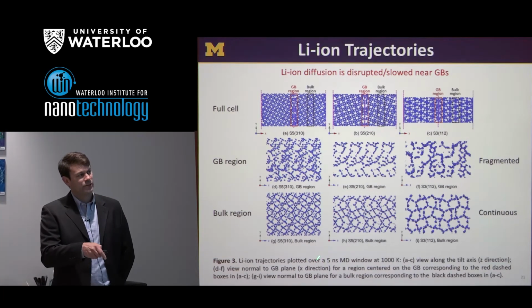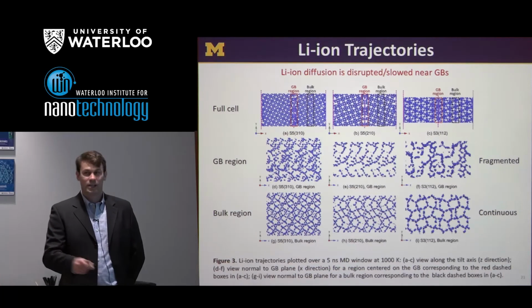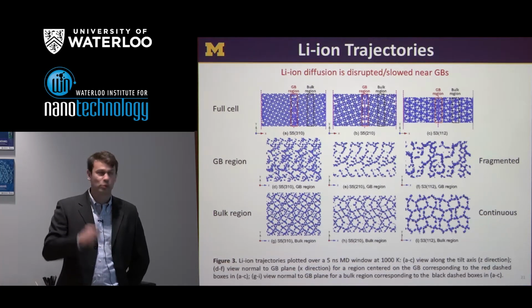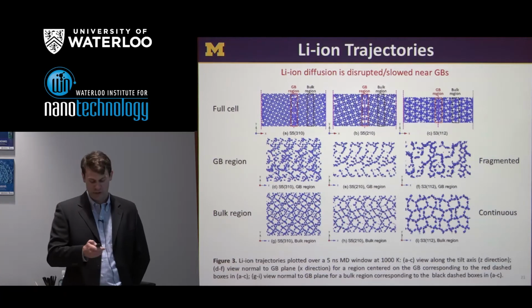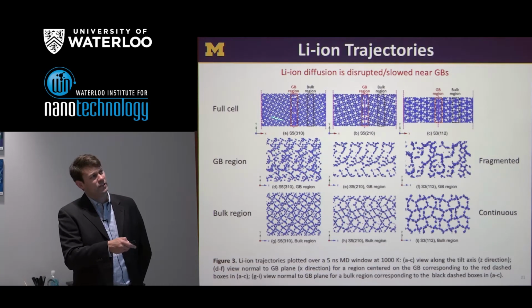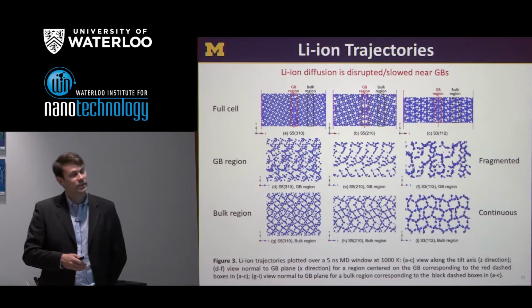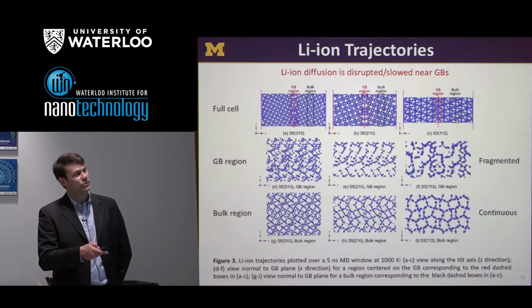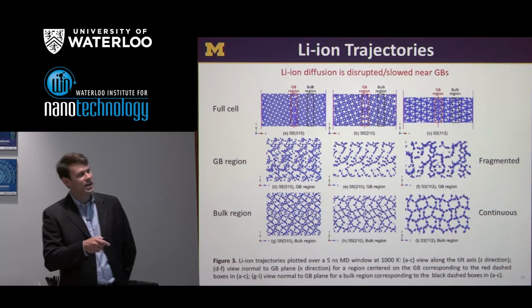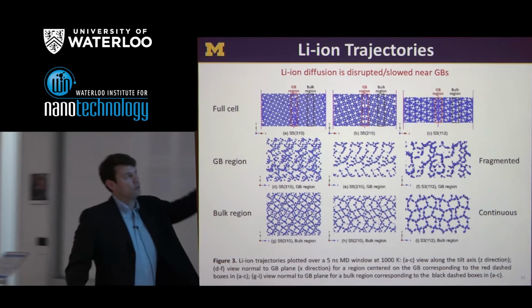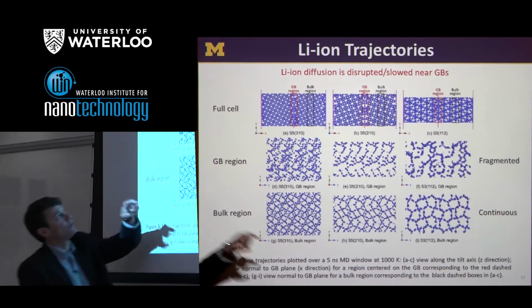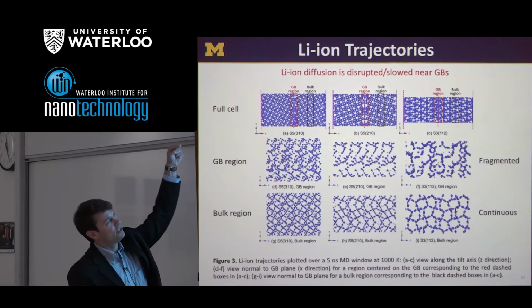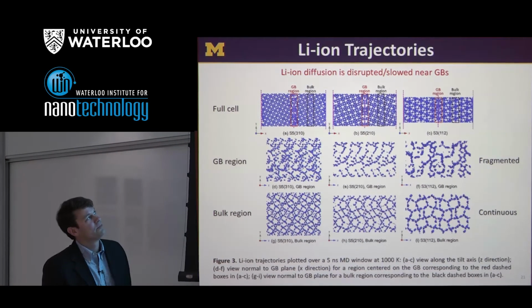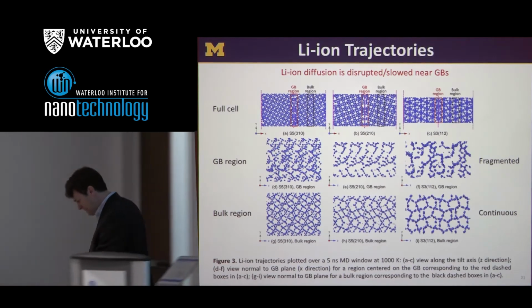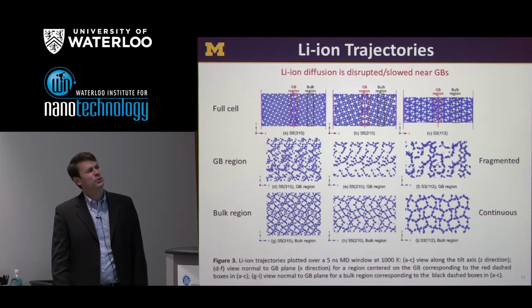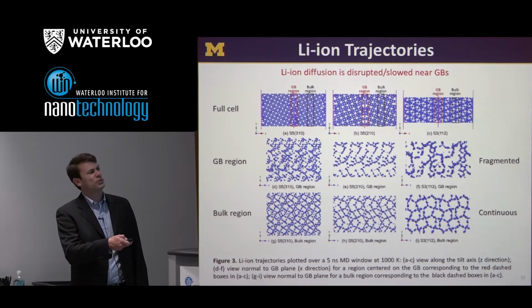So in this case, we use a 5 nanosecond MD window, and for each one of those steps, we plot a spot of blue to represent each lithium atom's position. And so, well, you can see at the top here that the blue basically fills the volume of the cell when we look along the tilt axis. But if now instead we look sideways, so in these two bottom rows, I'm looking, well, if I were up on the top, I'd be looking to the right or looking horizontally. So looking perpendicular to the tilt axis in these two rows.